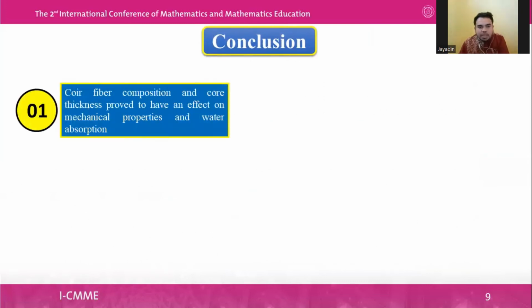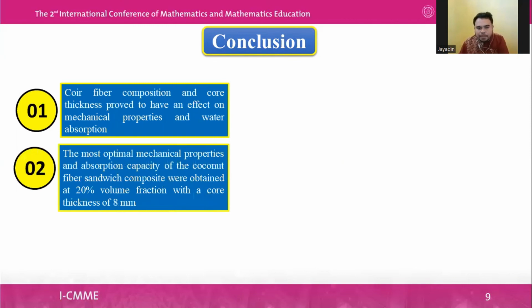Conclusion. Research on the manufacture of sandwich composite from coconut coir fiber and polyester resin with a skin layer has been carried out. Core fiber composition and core thickness proved to have an effect on mechanical properties and water absorption. The most optimal mechanical properties and absorption capacity of the coconut fiber sandwich composite were obtained at a 20% volume fraction with a core thickness of 8 mm,